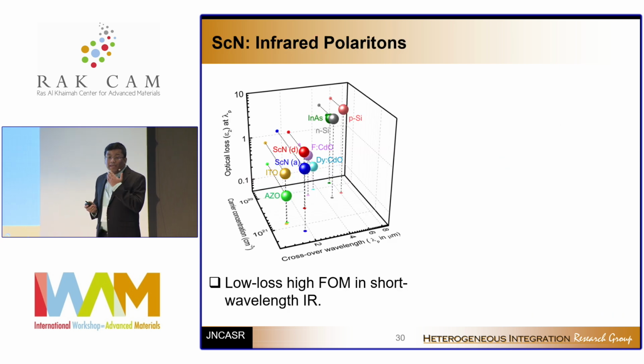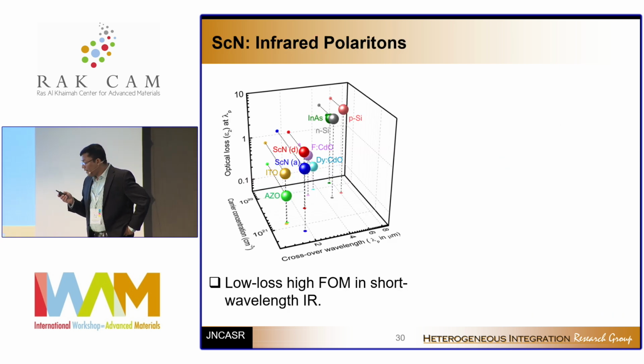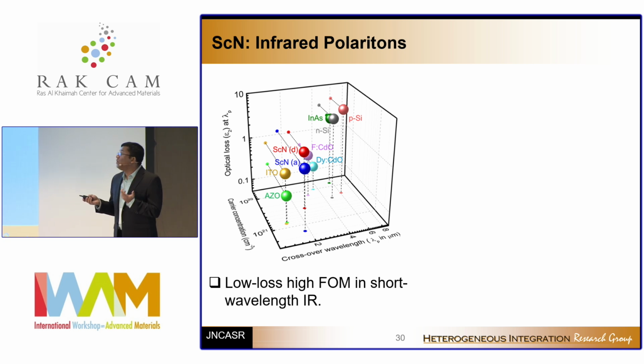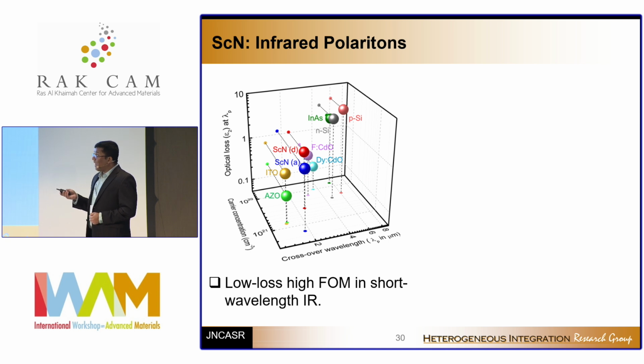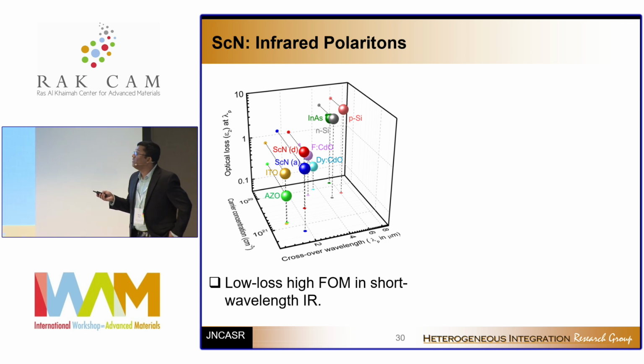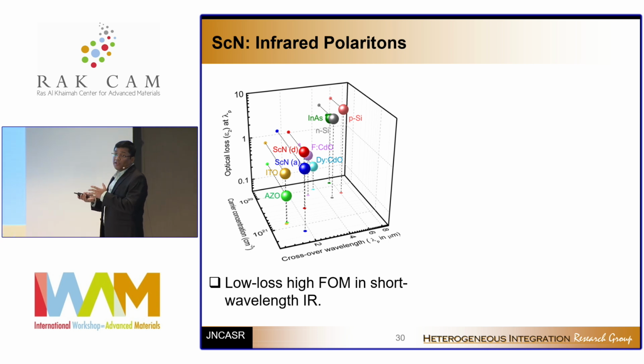So how does it compare? Well, if you look at the near-infrared or infrared plasmonic materials, for example, indium tin oxide, aluminum-doped zinc oxide, or cadmium oxide, scandium nitride's property is pretty much close to, or in some cases better than, many of these materials. So today, it may not be used in some devices, but we can easily foresee a future when scandium nitride can find application in this sort of devices, because just remember, in the infrared spectral range, there are very few materials which work as well as you need.